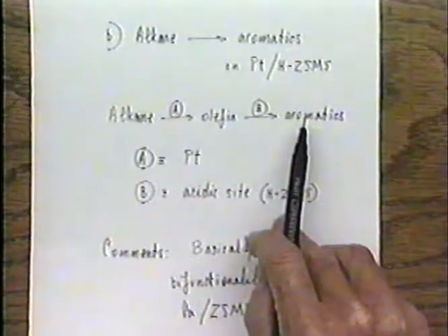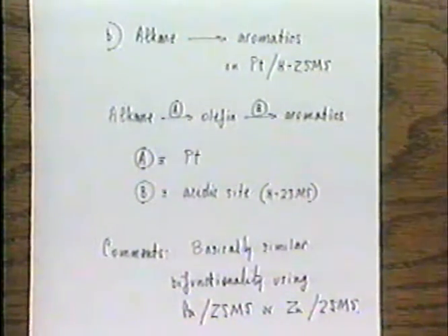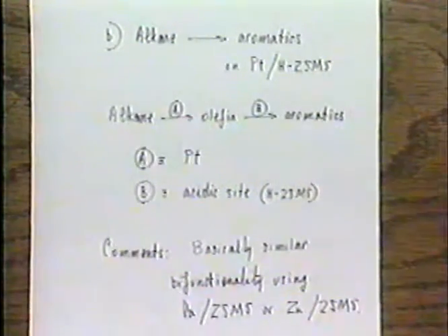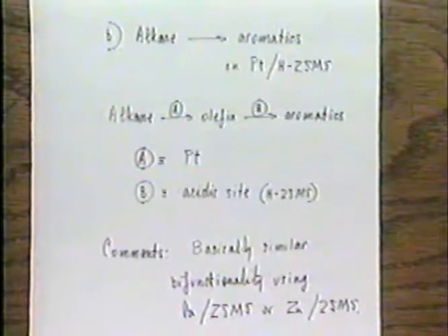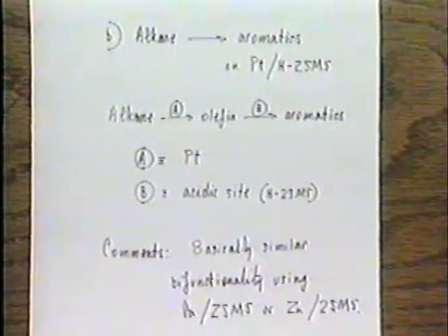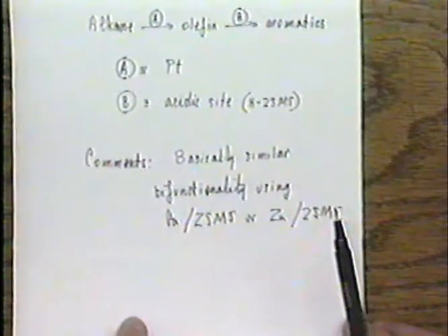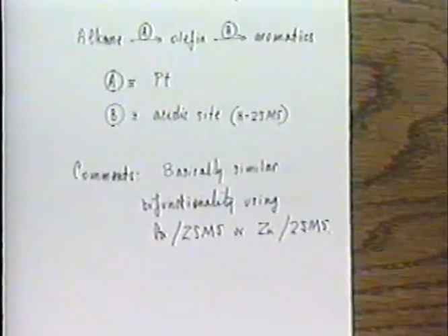And that can be readily done, and the only thing you have to again remember is that the platinum will be functioning as a hydrogenolysis site also, and again, to repeat what I said before, one might have to do something to try and poison or otherwise remove those sites on the platinum surface which yielded the hydrogenolysis reaction. But that reaction can be done reasonably well. In fact, for reasons that are partly economic, that process is a quasi-commercial process.